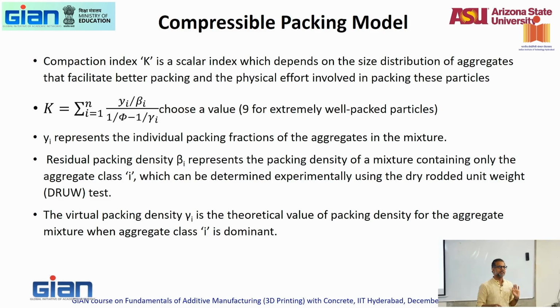So you find the maximum. Now, if I go to number 8 and do the same experiment, what's the maximum number I could expect? Same, right? Because with number 8, only the size has changed. The shape is still the same. So 0.74 is the maximum that you can get. You typically will get 0.65, 0.66. Generally, if you do aggregates, that's what you get. So y sub i is all of those values. If I'm using 3 different aggregates, y sub i is y1, y2, y3.